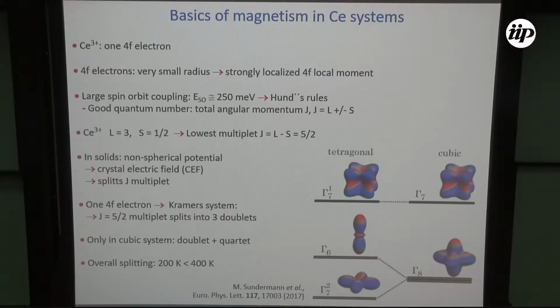I will first go a little bit through the basics of cerium magnetism to get the important point in this compound. Cerium has one f electron. Because the f electron has a very small radius, this leads to a strongly localized 4f moment. Because one has a very large spin-orbit coupling, one has to apply Hund's rules. The good quantum number is the total angular momentum J, which is equal to L plus or minus S. For cerium 3+, we have L equals 3, S equals 1/2, and therefore the lowest J multiplet is 5/2. We have J equals 5/2.